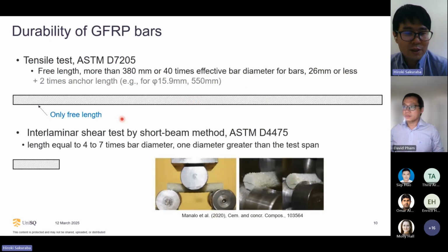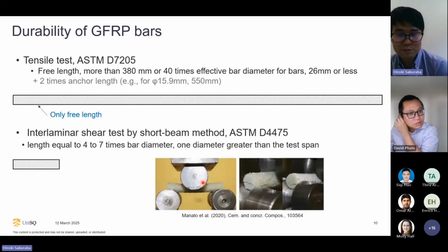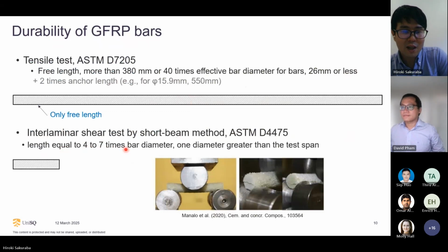So it is practically impossible to take a long specimen from actual concrete bridges. But on the other hand, we also have an interlaminar shear test by short beam test, as shown in this picture. This needs only a length equal to 4 to 7 times the bar diameter. So if we take a concrete core sample, diameter 100 millimeters, we can test interlaminar shear strength from a sample taken from actual concrete structures. So in my study during visiting research, I focused on interlaminar shear because this can be taken from actual concrete structures.